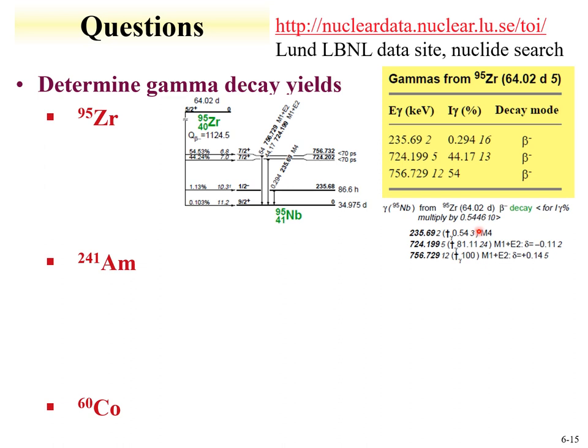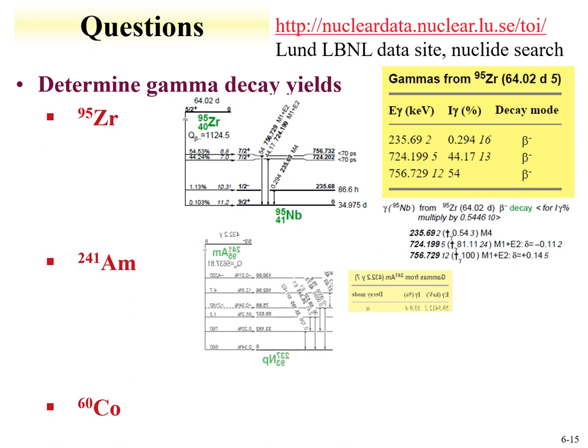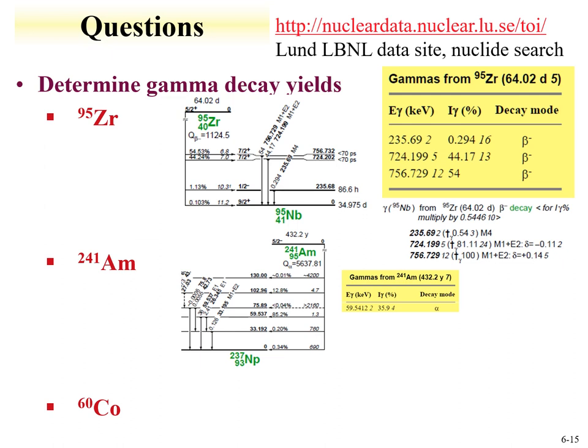We can also look for the data for americium-241, which decays prominently by a 59.5 keV photon. If we go to the Lawrence Berkeley site, we see that the gamma intensity is 35.9%. Comparing this with what we see from the table of the isotopes, here's americium-241. This is a truncated table, and it decays 85.2% of the time to this 59.5 keV excited state. However, only 35% of the time this photon decay is observed.